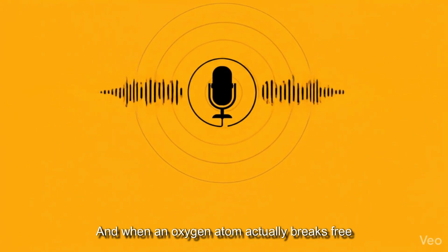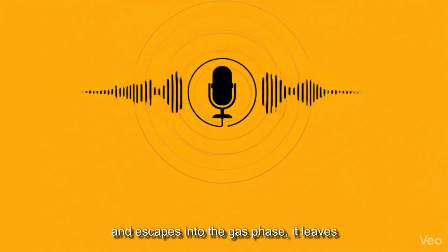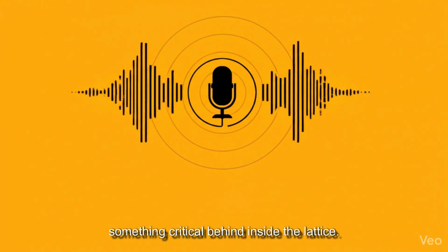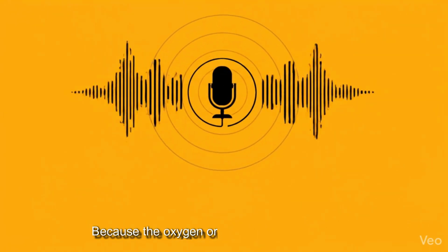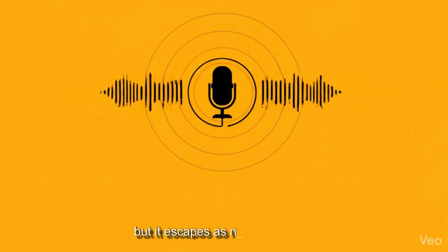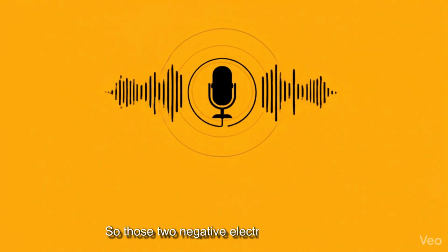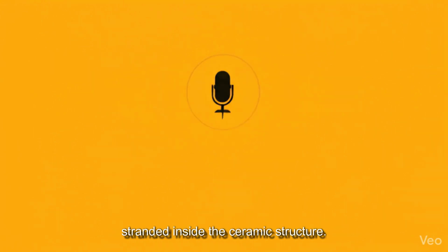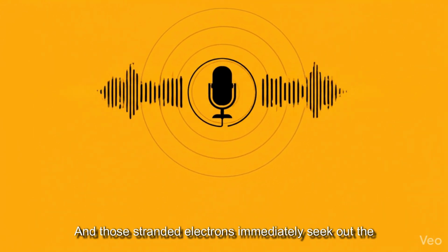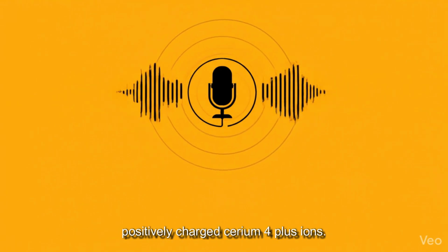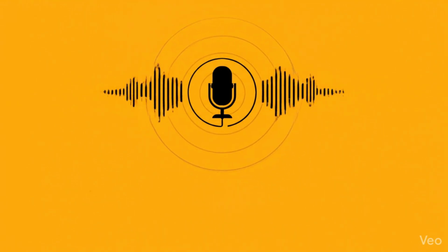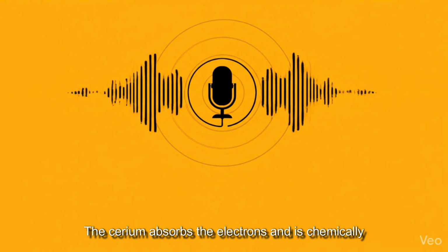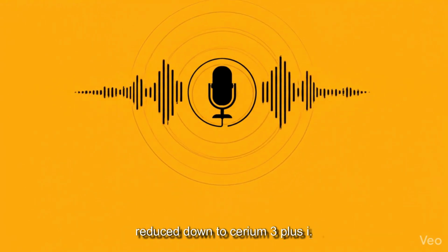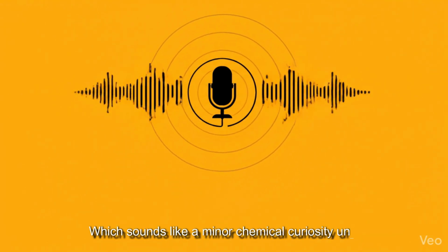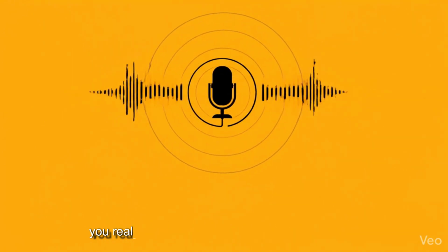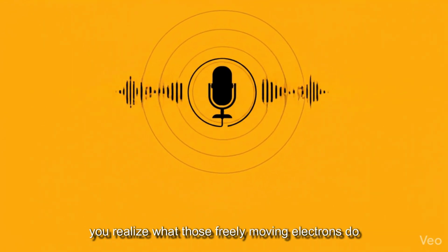Exactly. And when an oxygen atom actually breaks free and escapes into the gas phase, it leaves something critical behind inside the lattice. Its electrons. Because the oxygen originally had a 2- charge, but it escapes as neutral O2 gas. So those 2 negative electrons are just left stranded inside the ceramic structure. And those stranded electrons immediately seek out the positively charged cerium-4+ ions. The cerium absorbs the electrons and is chemically reduced down to cerium-3+ ion.